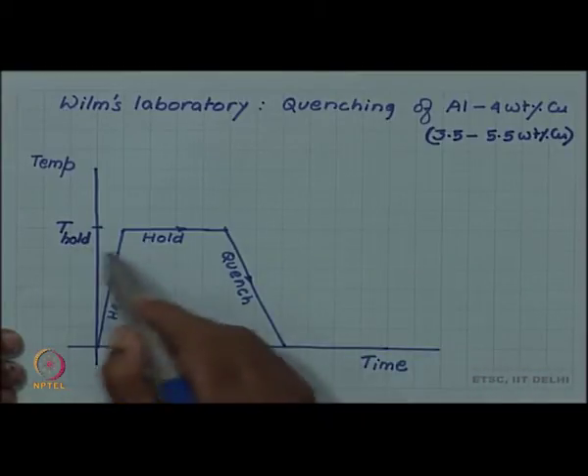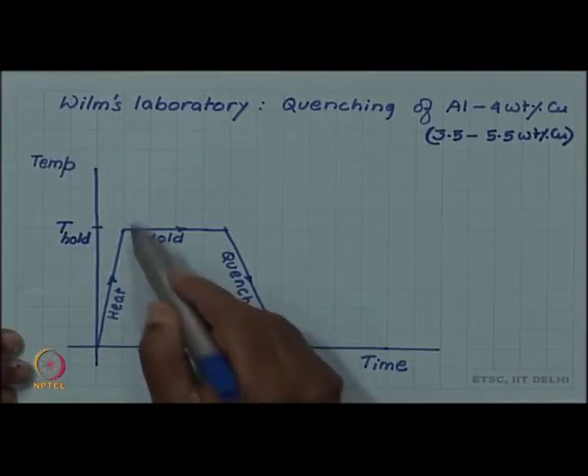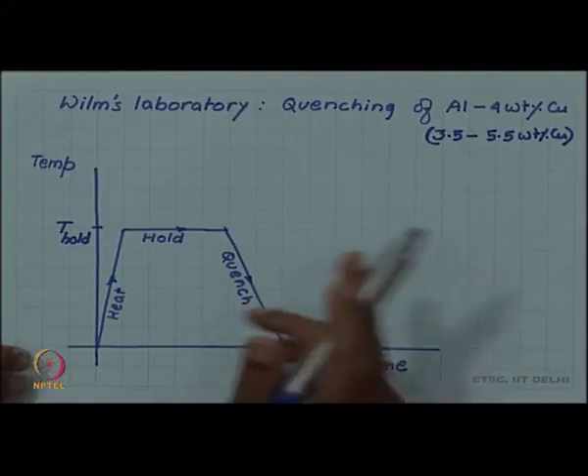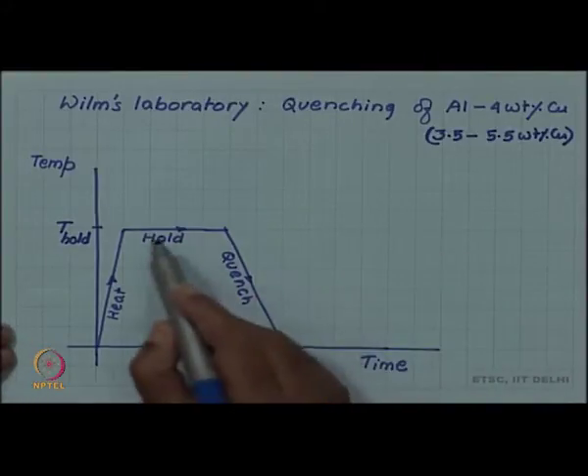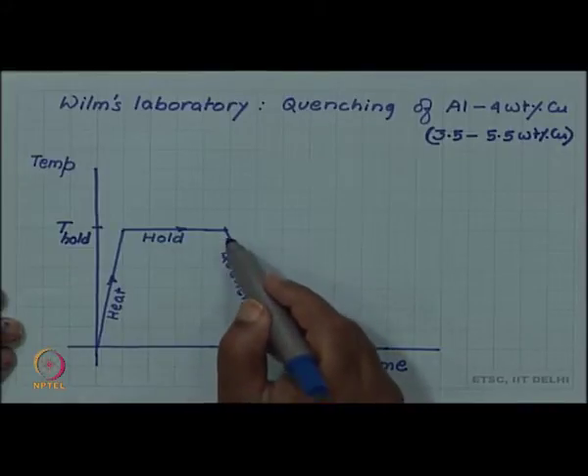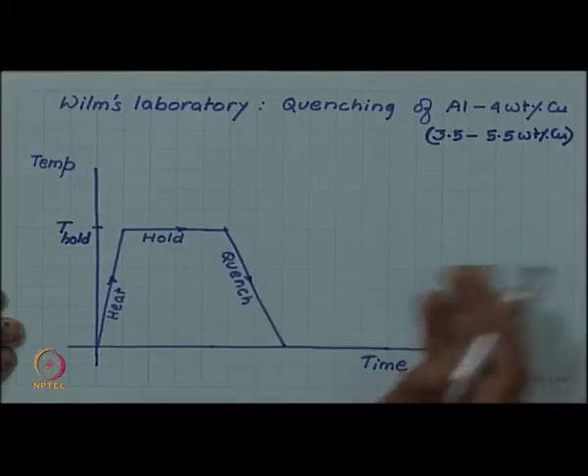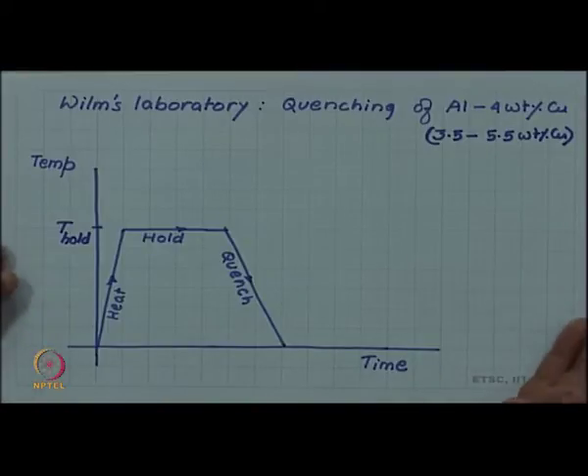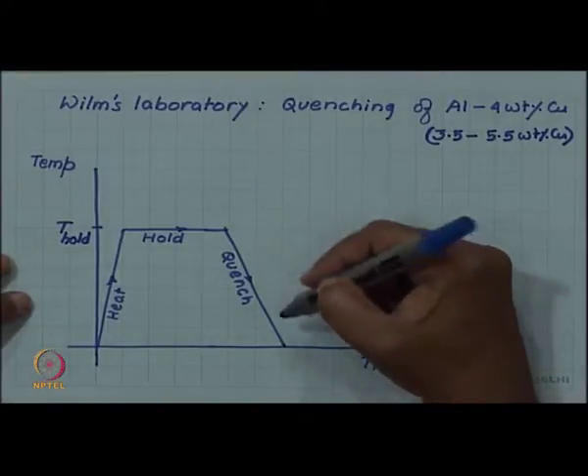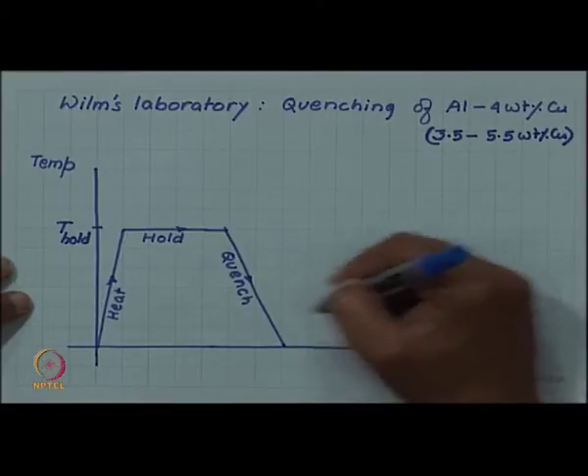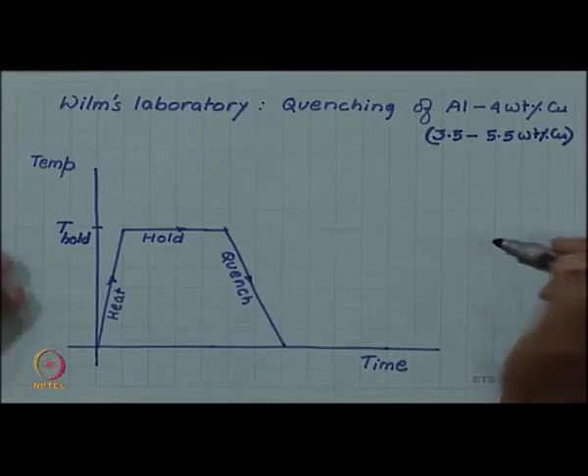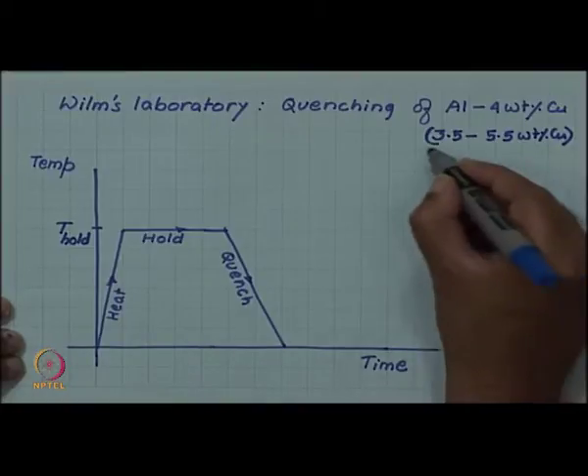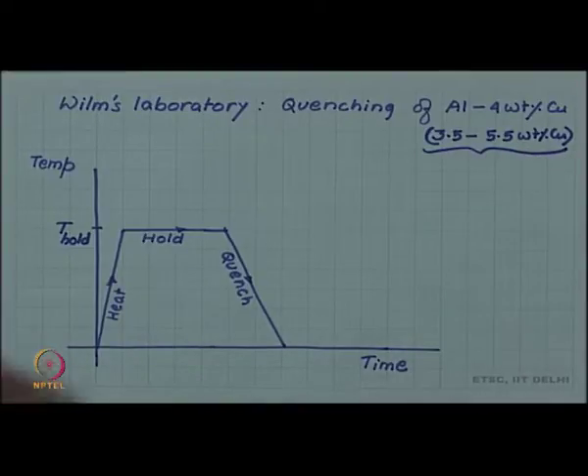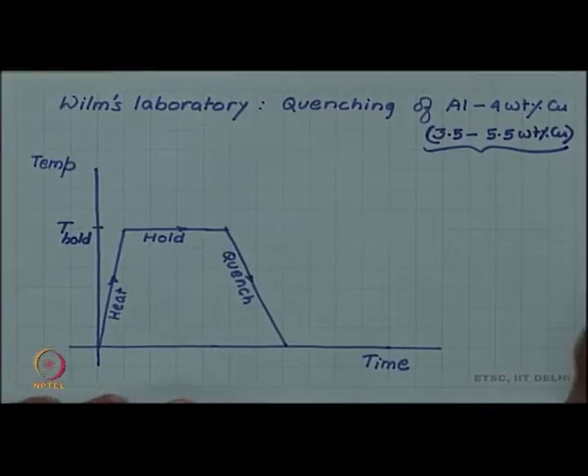So is this holding temperature important? So he varied the holding temperature. Similarly, again in austenite, you find that unless and until austenite is quenched rapidly enough to miss the nose of the TTT curve, martensite will not be produced. So the quenching rate should be sufficiently fast. So he varied the quenching rate. With all these experimental variations, and of course he had variation of alloy content also, none of these runs gave him any success.